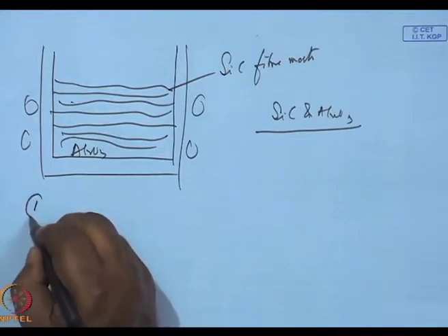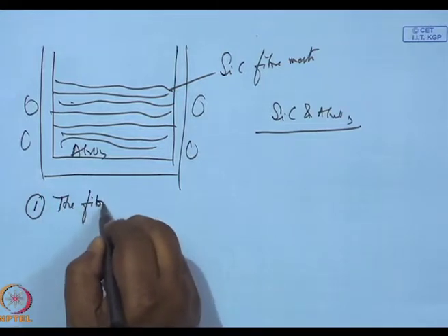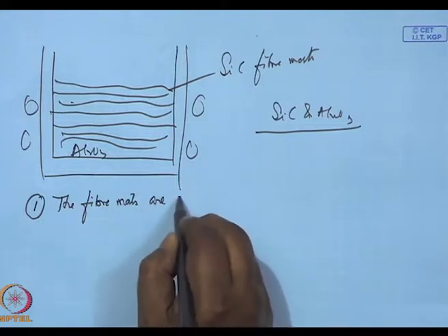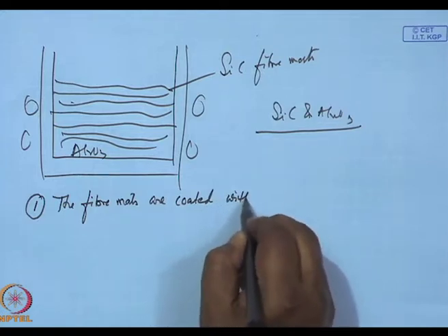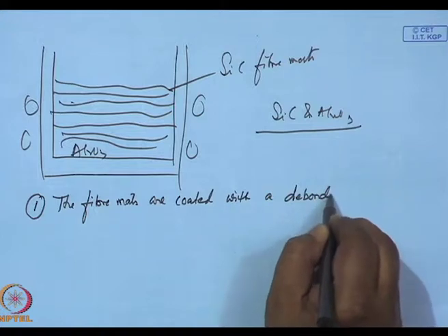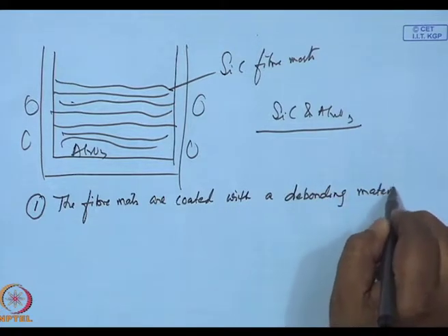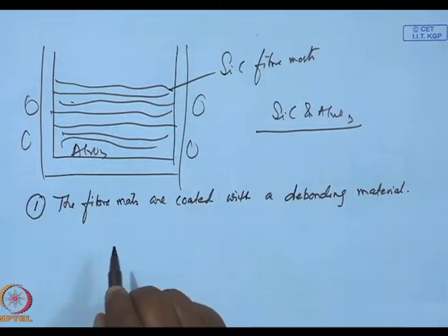In chemical vapor infiltration, one of the first things done is that the fiber mats are coated with a debonding material. The simple reason is, if this is the alumina matrix and there has been a reaction between the aluminum oxide matrix and the silicon carbide, when the fracture goes through the alumina, it will also go through the silicon carbide. However, if there is a debonding material, what would happen? The fiber would slide out and the basic structure would be retained.